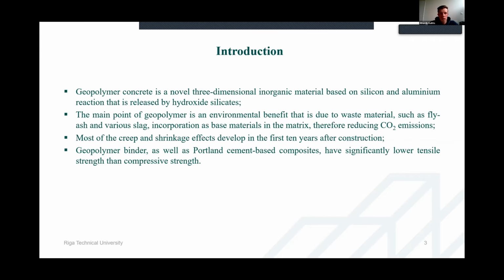As for the long-term properties, such as shrinkage, I'm guessing that most of you know that for the first 10 years after the structure is made, the main creep and shrinkage take place. And also as for the tension tests for long-term properties, as with Portland cement-based composites, geopolymer-based composites also have significantly lower tensile strength than compressive strength. Therefore, even if the element that is tested is made quite thick, it's still quite brittle, and if it isn't handled as well as it should be, it can develop some unwanted cracks, and therefore the test is ruined.